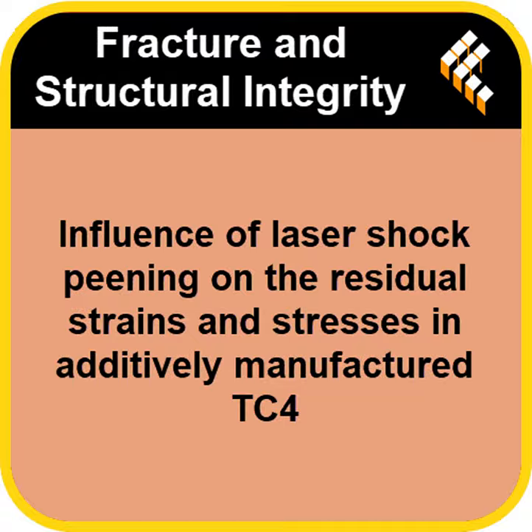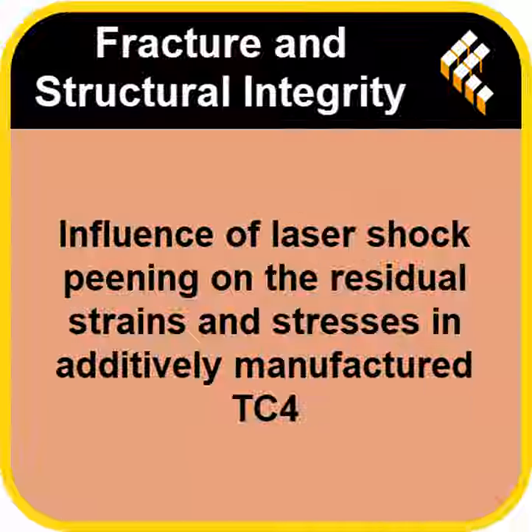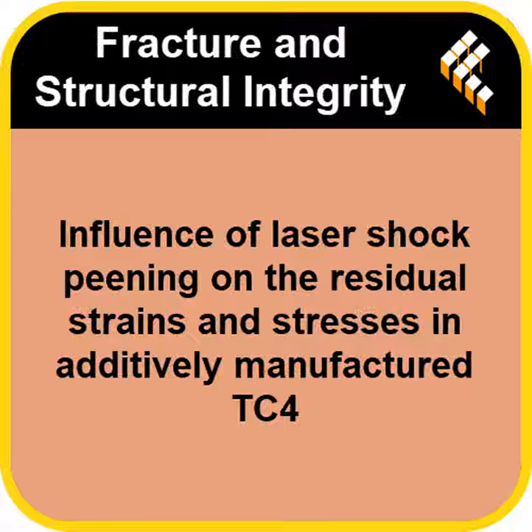Fundamentally. So the material starts with flaws. We need post-processing to fix it. People might use heat treatment, maybe shot peening, kind of like sandblasting with metal balls. Those are common. But they can have downsides like excess heat or just surface changes. Why is LSP the focus here? What makes it advanced? Well, LSP tackles the stress deep inside the material, but critically, it does it without significant bulk heating, which can mess up the fine-tuned microstructure you got from AM. It's a surface treatment, yes, but it uses these incredibly high-power short laser pulses to force the material to deform plastically. Plastic deformation, meaning it changes shape permanently on a tiny scale. Right, and that deformation generates the good kind of stress, compressive stress near the surface.